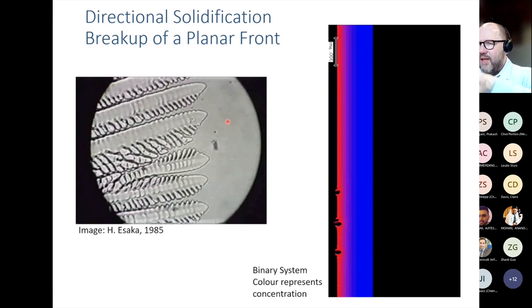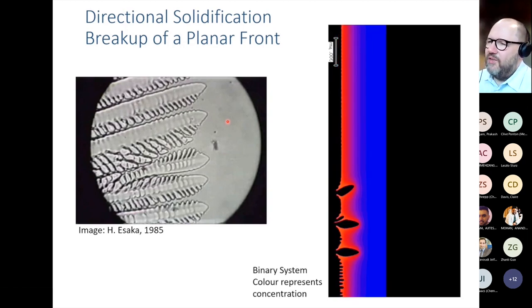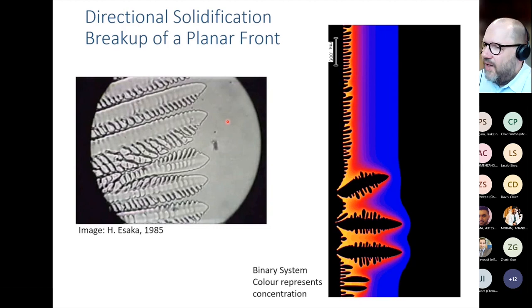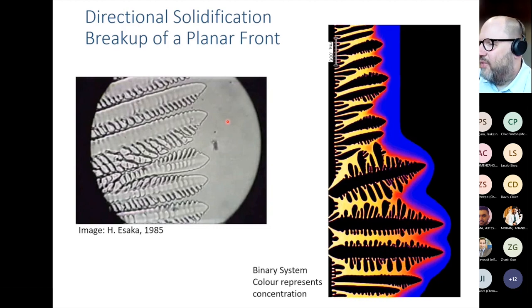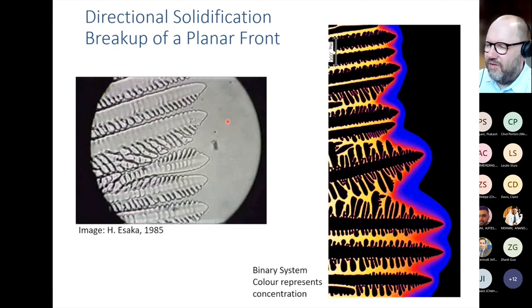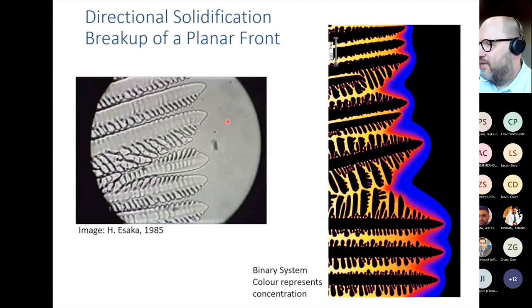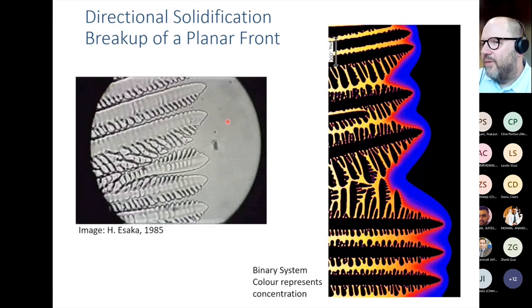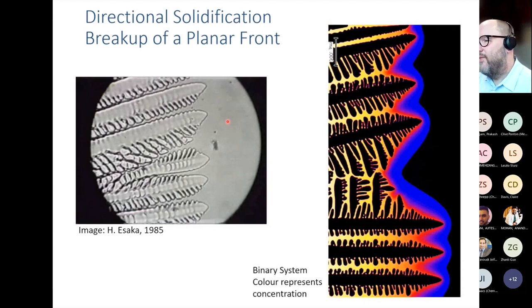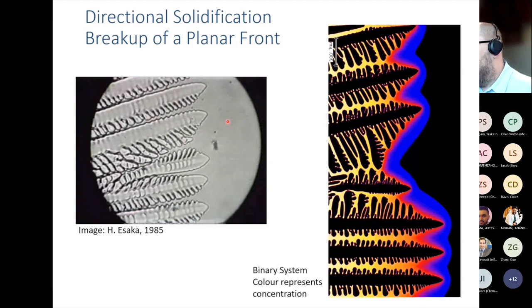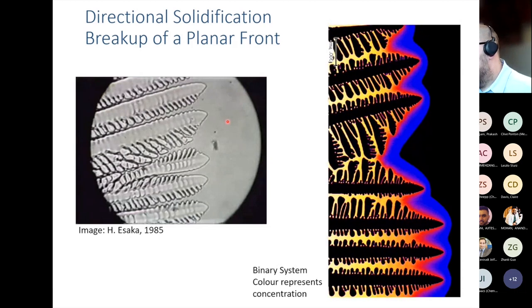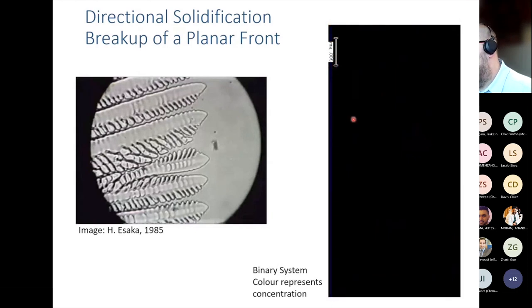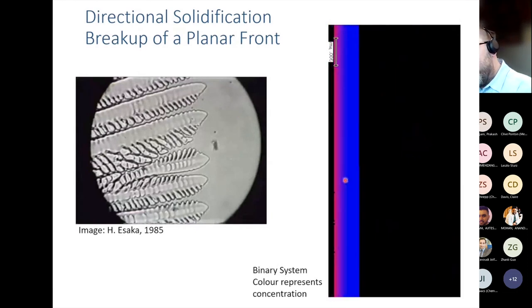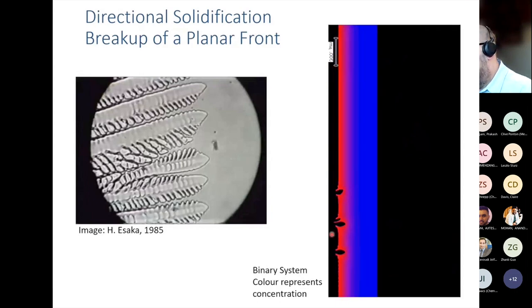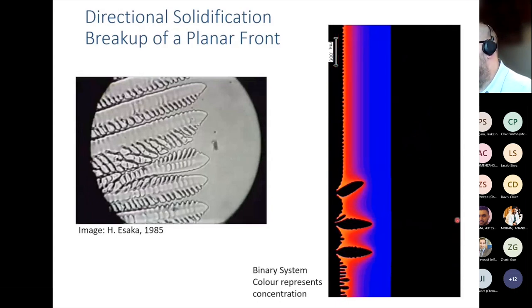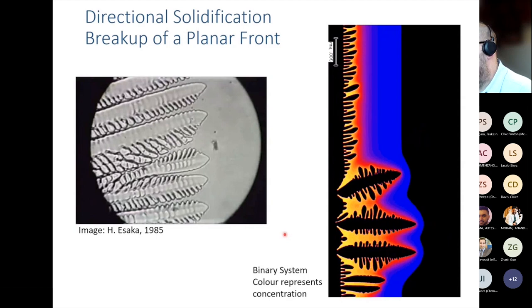Sorry. So here we're going back to that transparent model system. I'd like to point out that this is a demonstrator simulation again. It's not modeling exactly the same alloy or the transparent model system as we see in the micrograph, but it's solidifying under similar conditions. So we see initially here we got two grains with different orientations. One perfectly aligned to the heat flux direction. We got high temperature on the right, low temperature at the left.